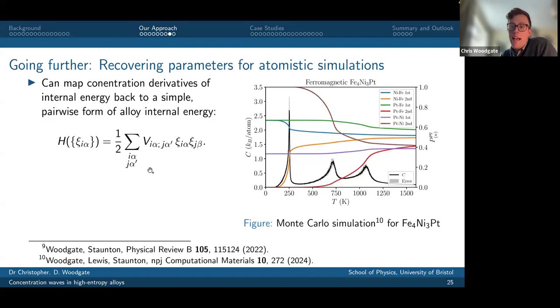Okay, good. The nice thing about doing those derivatives of the internal energy as evaluated within the CPA is that actually they give me access. I evaluate them in reciprocal space for reasons to do with the translational symmetry of the underlying lattice. But if I back Fourier transform, if I go back to real space, I can recover an effective pair interaction. Okay, so an Ising-like interaction between atoms on different lattice sites in the alloy. So V_{iα,jα'} describes the interaction of an atom of species alpha on site i with an atom of species alpha prime on site j.